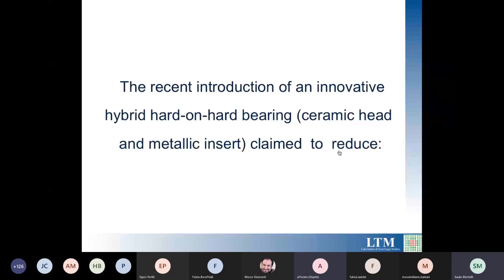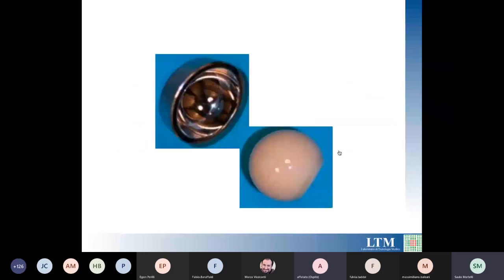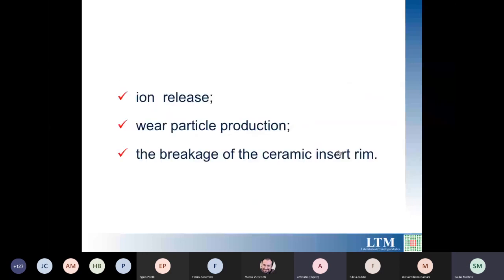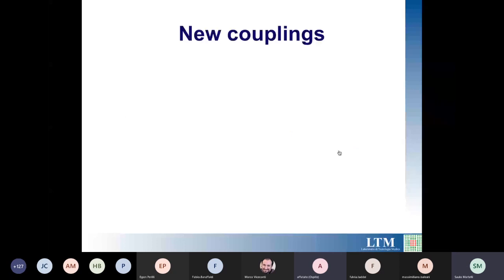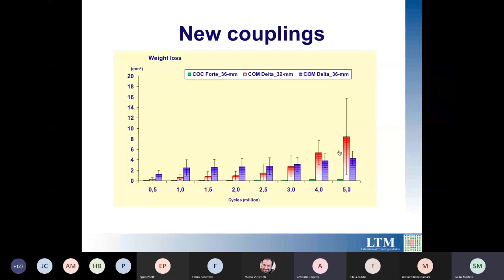And the recent introduction of an innovative hybrid bearing, ceramic and metallic interface, claims to reduce the ion release, wear particles, and the breakage of the ceramic insert rim. So these new couplings, ceramic against metal, were tested with our simulator and showed bad results in comparison with the pure alumina.